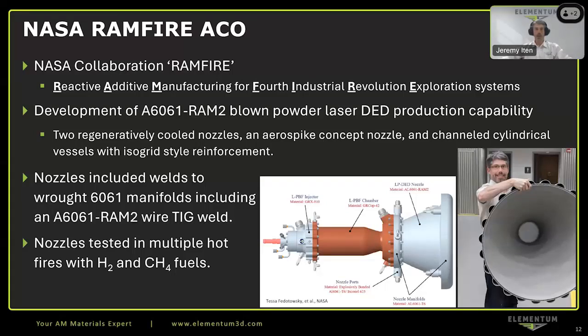The nozzles included welds to wrought 6061 manifolds, including an A6061 RAM2 wire TIG weld. So the Elementum 3D wire was used to weld some of these materials. I'll touch on that a little more later as well. And the nozzles were tested in multiple hot fires with hydrogen and methane fuels. And you can see the assembly there below. The part on the right is the DED printed nozzle from the aluminum RAM material. In the center is a GR-COP 42 combustion chamber. We also produced that. And then on the left is a GRX-810 injector component. So this was really a merger of 3 advanced AM type technologies, and I think a really great, exciting project to be a part of.